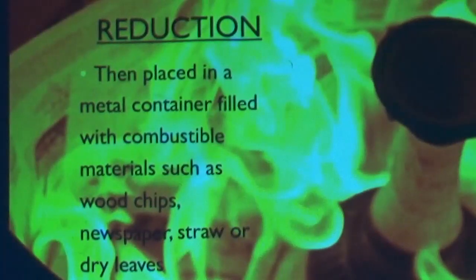It's where you get this black network of lines, or any area that's not covered turns black. And it's not just a soot covering, it's not looking like charcoal. It is actually in the clay. It has gotten chemically placed into the ceramic work. Now sometimes it's not always advantageous. Sometimes it doesn't go completely black, sometimes it turns brown or yellow, depending on what you're using. But I prefer to go with this really stark contrast of black and white, or as close as I can. So I'm really going for that really good char.